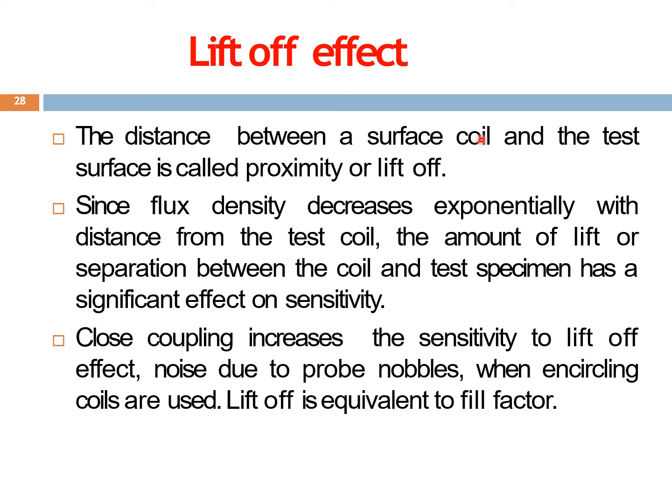The surface coil is actually the primary source of magnetic field, and the distance between the coil and the test specimen is known as proximity or the liftoff. Now, as we discussed before, the eddy current flux density decreases exponentially with distance from the test coil. That is, as the distance from the test coil increases, the flux density decreases exponentially. So we need to control the distance between the surface coil and the test surface.